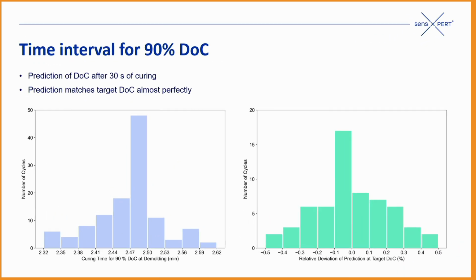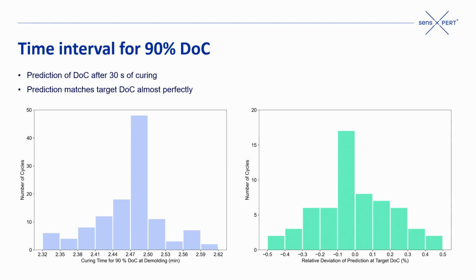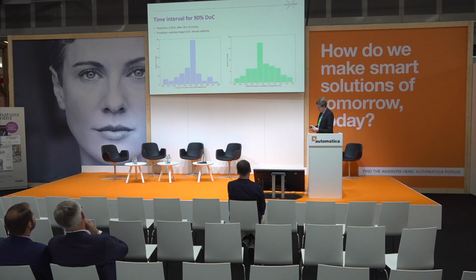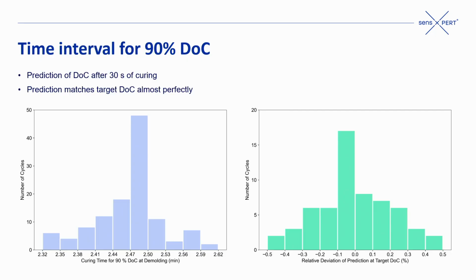And what we did is we applied our machine learning model here and did a prediction. First of all, this prediction works very well: we have a relative deviation between the prediction and the actual degree of cure of within plus or minus 0.5%. And what this in the end allows us is to basically remove the scatter here, right? So if we want 90% degree of cure, this is our good criterion, right? If we reach 90%, our part is okay.